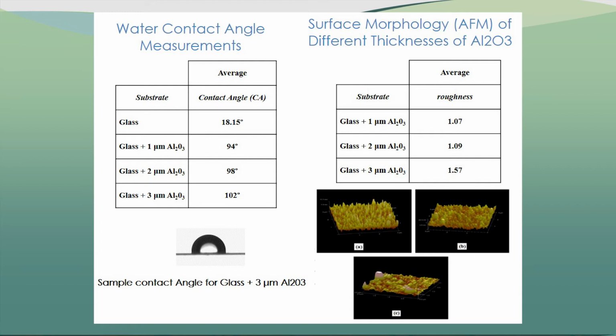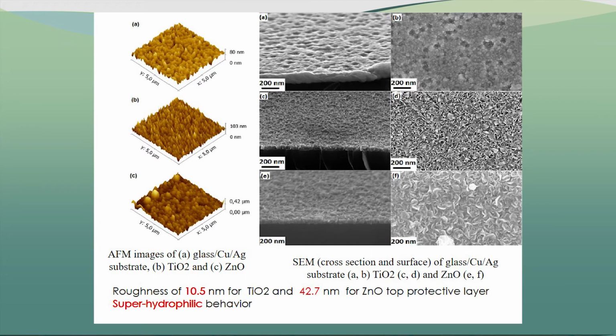If we look at the roughness of the surface, the roughness is quite low. This is why we didn't have a very high hydrophobicity for the aluminum oxide. Work is still going on to see if we can gain in roughness while keeping a good transparency. Here we look at the titanium dioxide and the ZnO, and you can see that you have some higher roughness, and we can also see some double structure for both of them. This explains the fact that when we put the droplets, we see a total spreading of the droplets on the surface, which is really creating the superhydrophilicity. This means that these two materials are very interesting in terms of the coating of the mirrors.